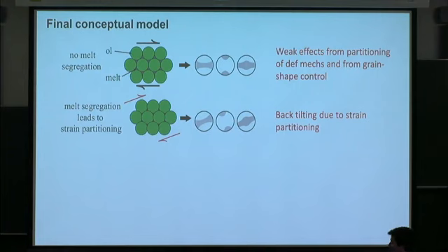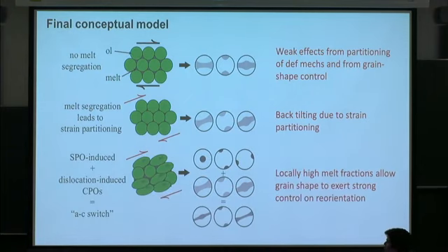But then when a high melt fraction region sweeps through, because of the anisotropy and interfacial energy, you develop crystallographically controlled elongation of your grains and shape-controlled grain rotations. Okay? And that wants to orient in this sort of direction. And so, the simple thing we want to do is think about these being summed together as you alternate from one process to the other. And conceptually, you get something like what we see. Right? So that's where we are. We're at a conceptual model.